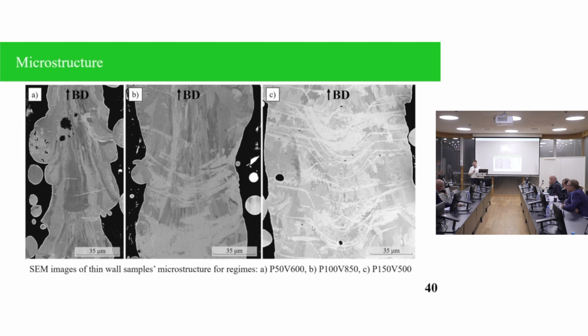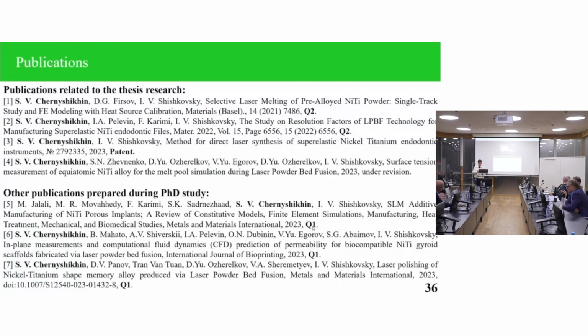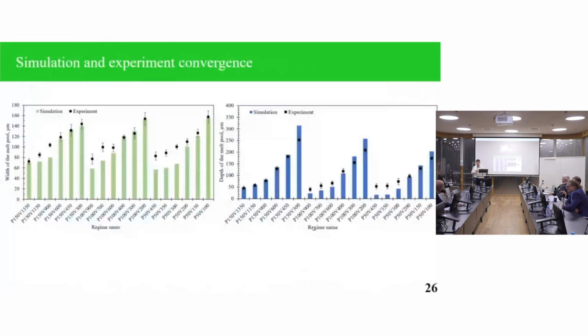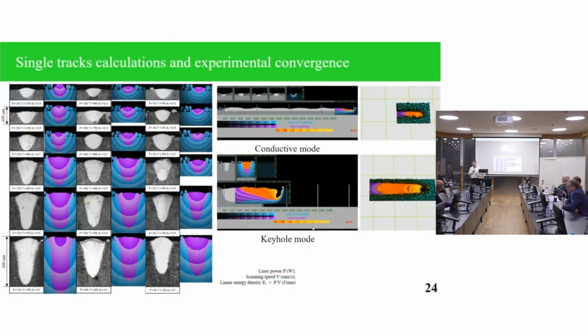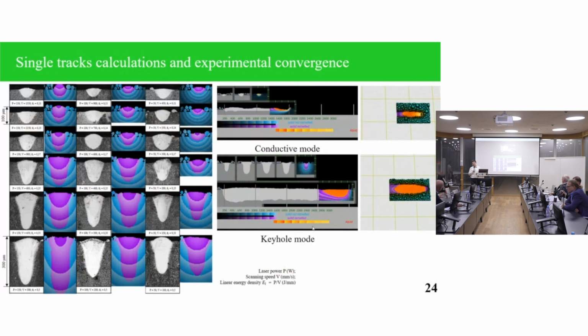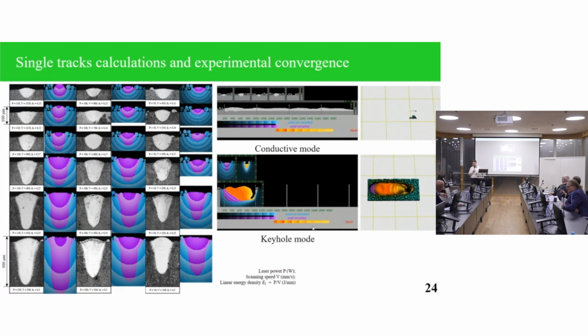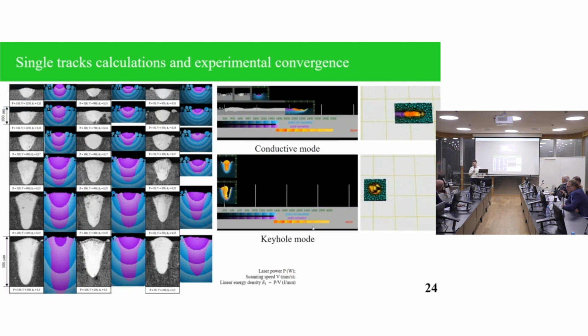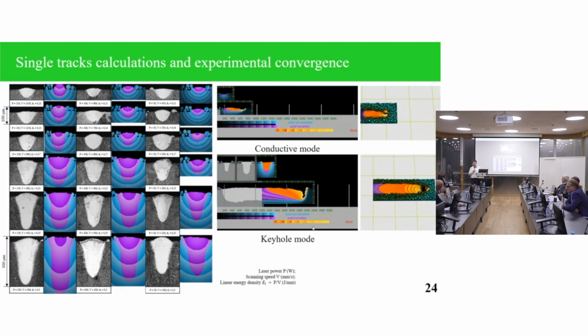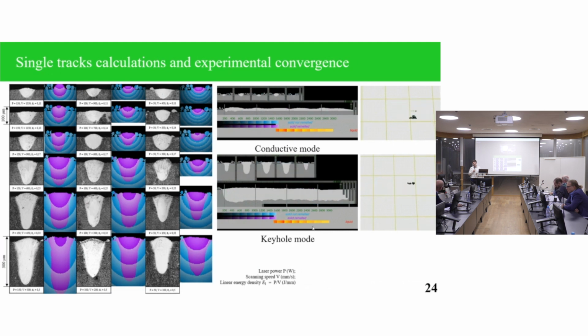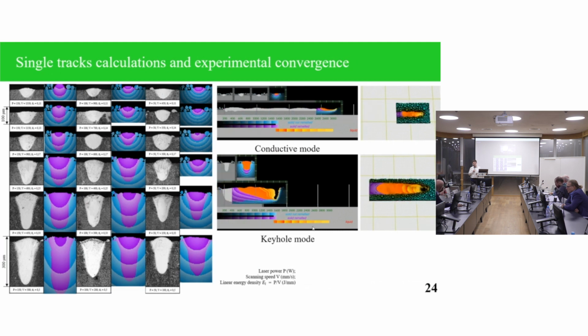I'm just saying that if you use it, it would be nice to compare it, at least to a certain extent, with your experimental observation. For example, it shows certain droplets on the surface, it shows a certain degree of roughness, it claims implicitly that it can predict it. And I'm just wondering to what extent. This is just one aspect. Thank you for opening that page. That's just one aspect, right? The shape of the melt pool, which is fair enough. But the question is, how far does one need to go in this direction if the geometry doesn't quite agree, even after all the attempts to calibrate it?